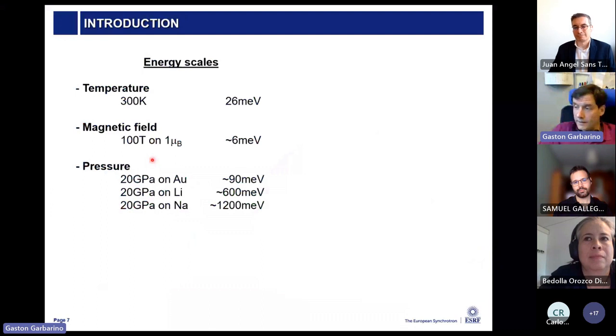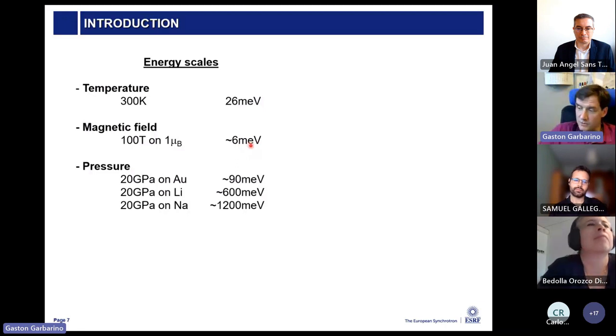So why is high pressure interesting? Just to give you some energy scales: if we are at 300 Kelvin, we can transform to energy, and this corresponds to 26 millielectron volt. If we apply 100 Tesla to a 1 Bohr magneton atom, the energy associated with this high magnetic field is of the order of 6 millielectron volt.